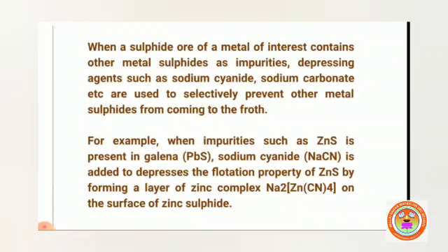Sodium cyanide depresses the flotation property of ZnS by forming a layer of zinc complex on the surface of zinc sulfide.